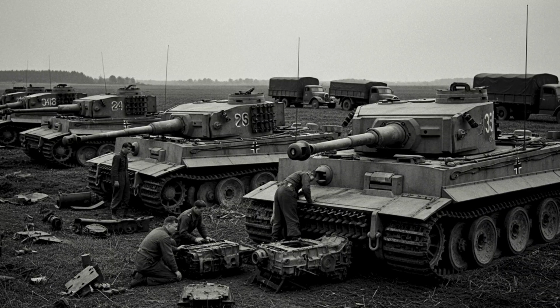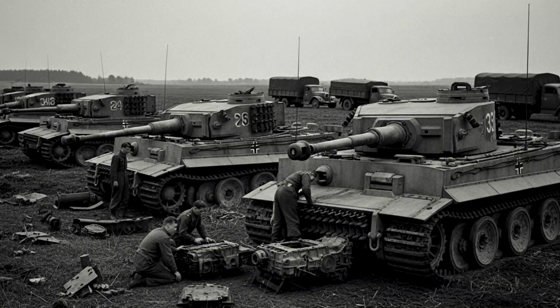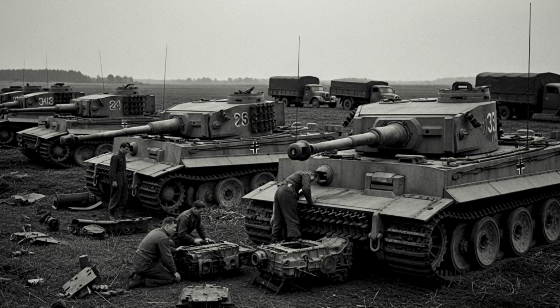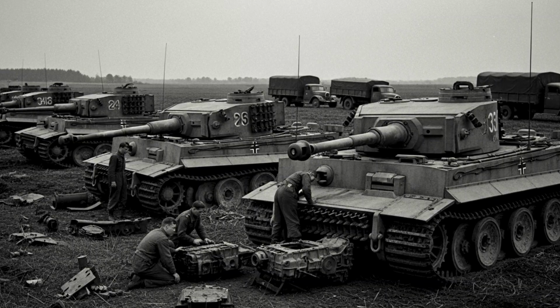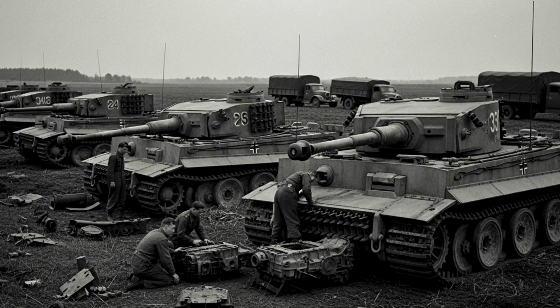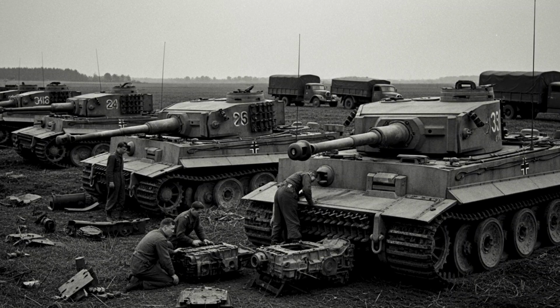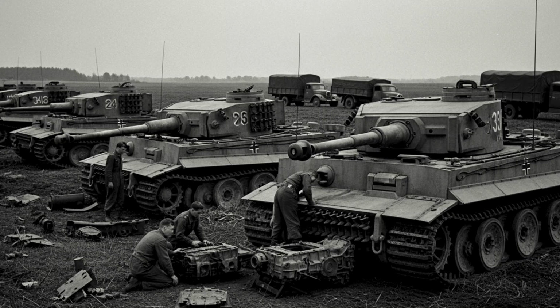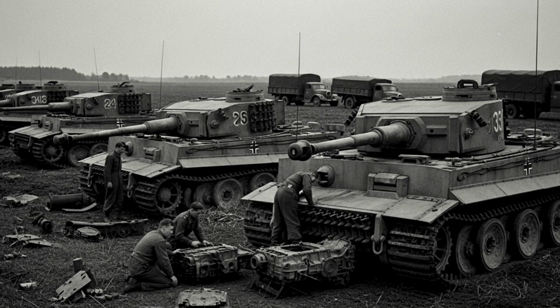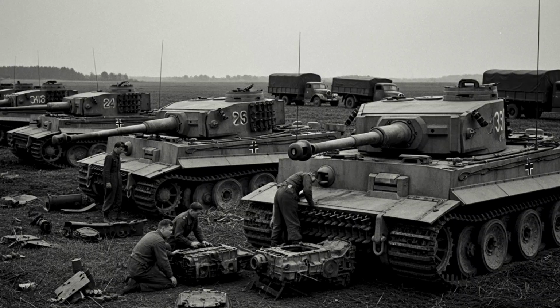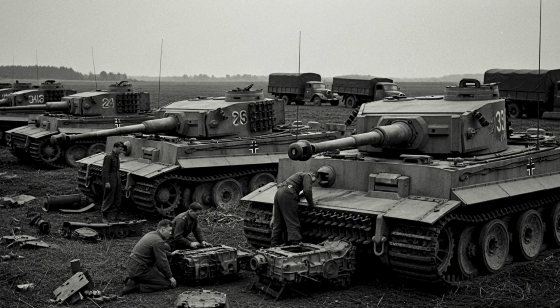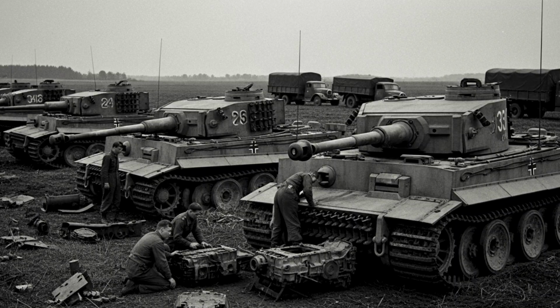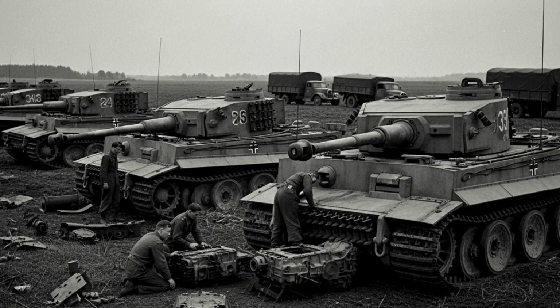Tigers kept breaking down in the middle of fights, far more often than normal tanks did. German reports after battles also noted the same issue. They mentioned that transmissions failed under heavy combat, blaming it on stress, poor maintenance, or lack of spare parts. They didn't realize the real reason was bad heat treatment of the gears, faulty metallurgy that made the transmissions ticking time bombs, waiting to break.